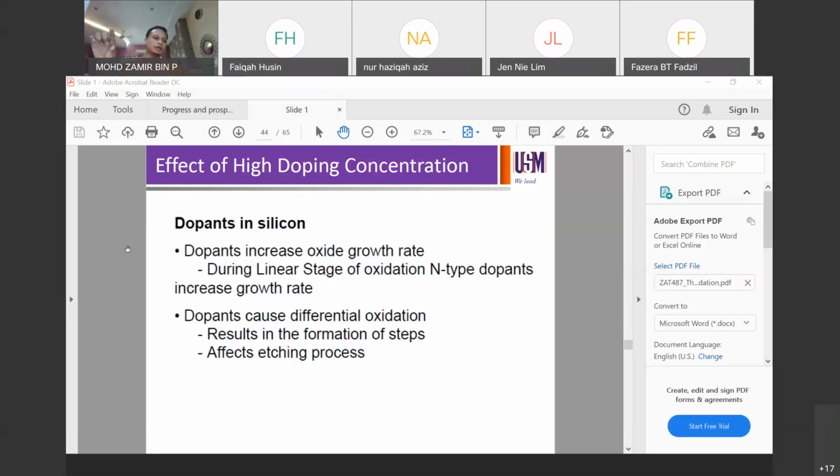It means you have a wafer, and you don't dope blanket throughout the surface with higher doping. So for example, if you have a wafer with 10^14 as your starting substrate, you don't dope blanket 10^16 or 10^17 on top. You might leave your wafer with 10^14 here, and then this region maybe 10^18, and then this one is 10^14 as the original starting wafer.